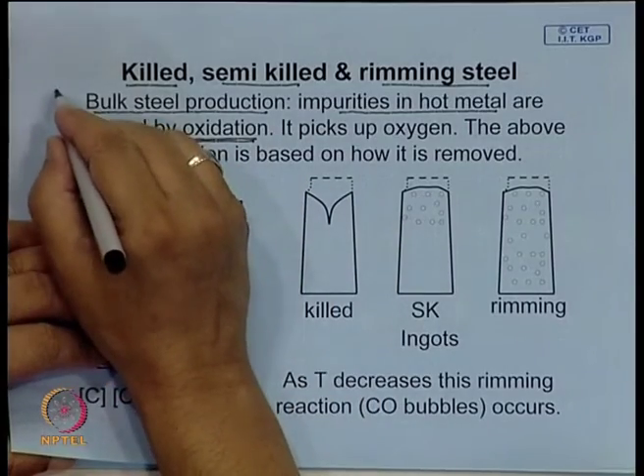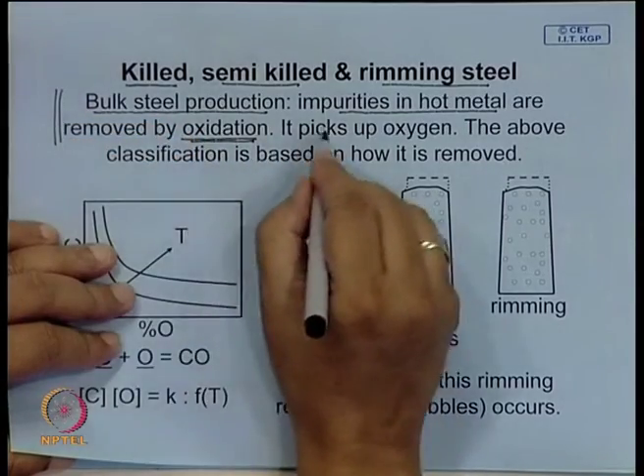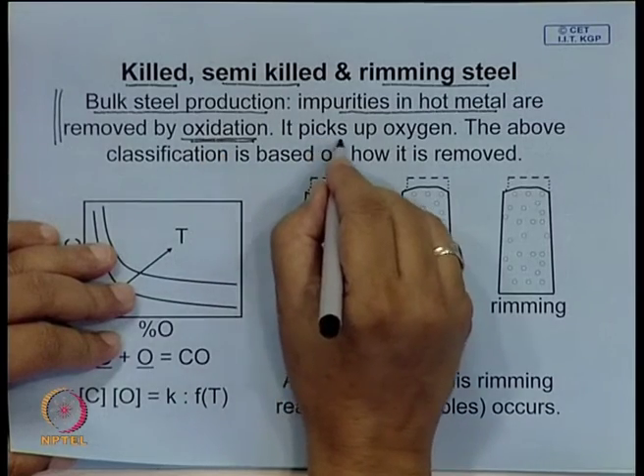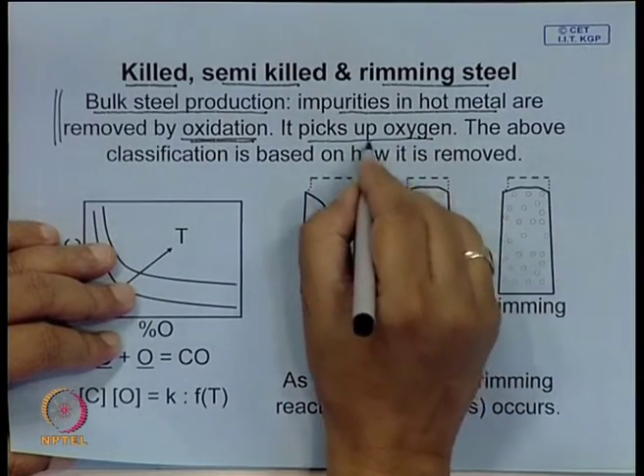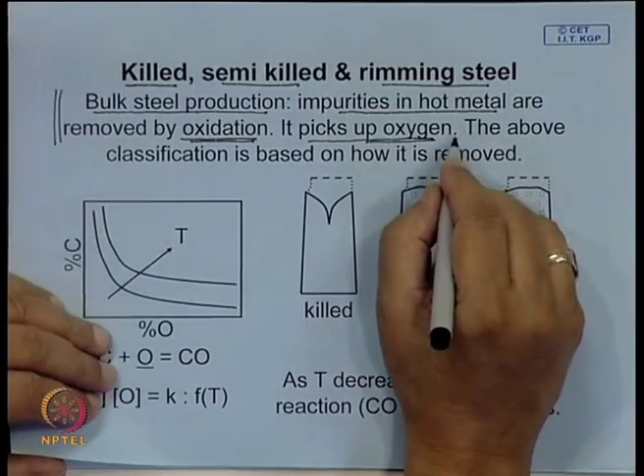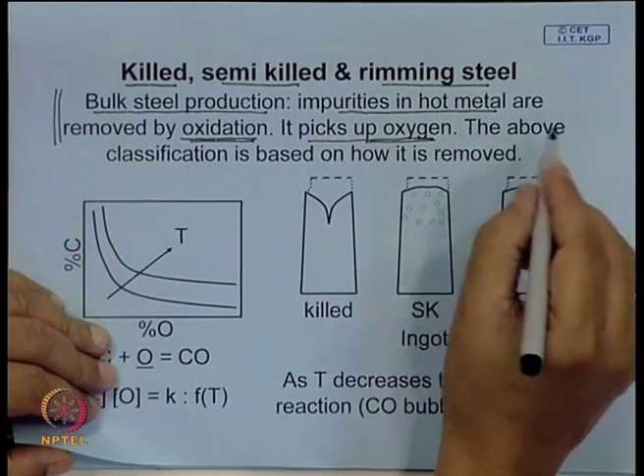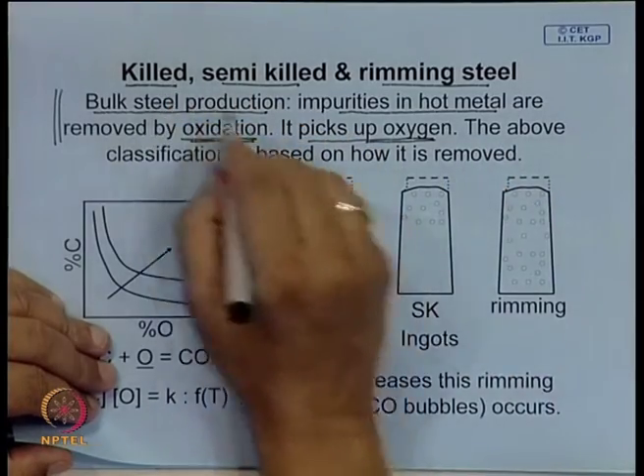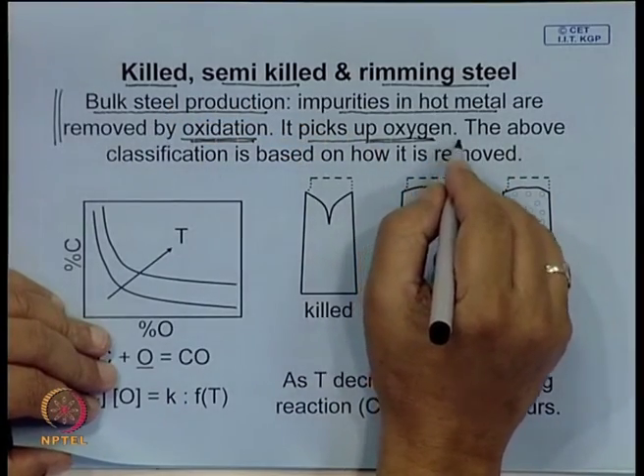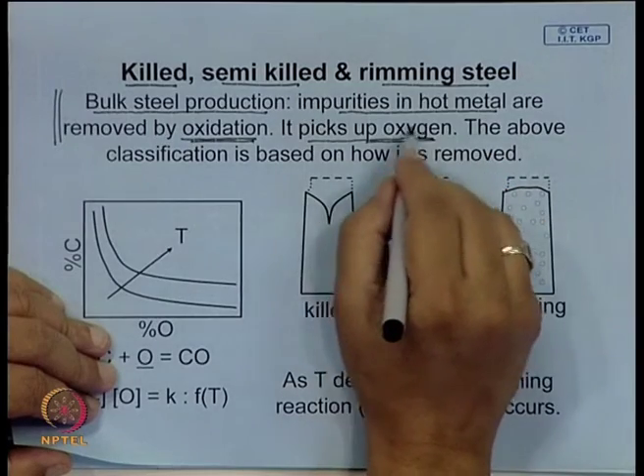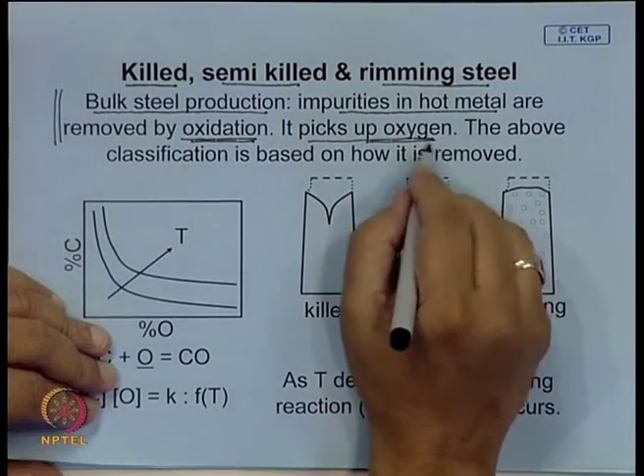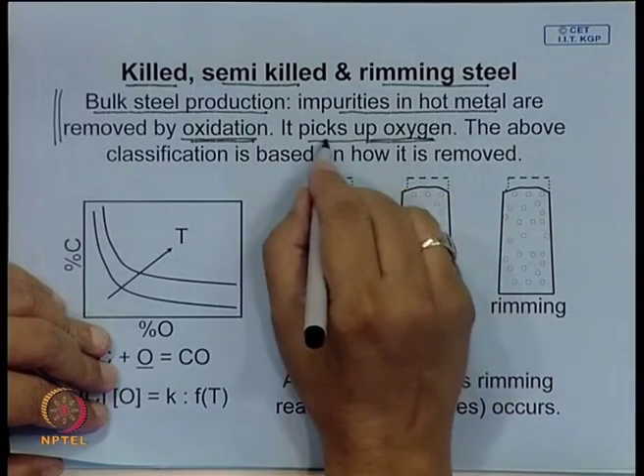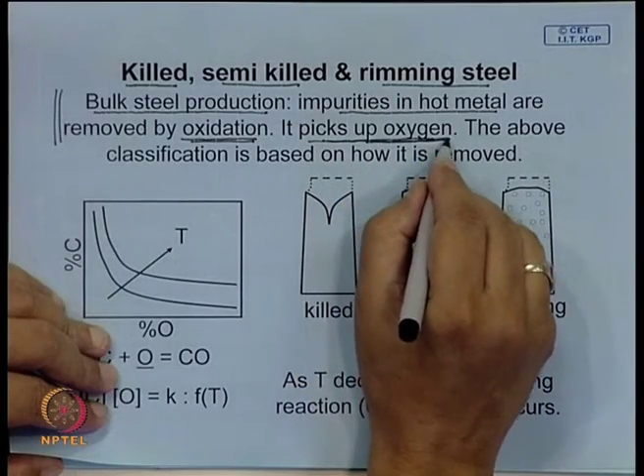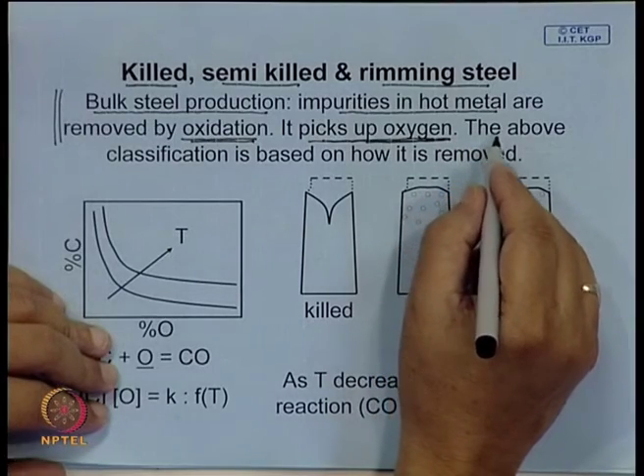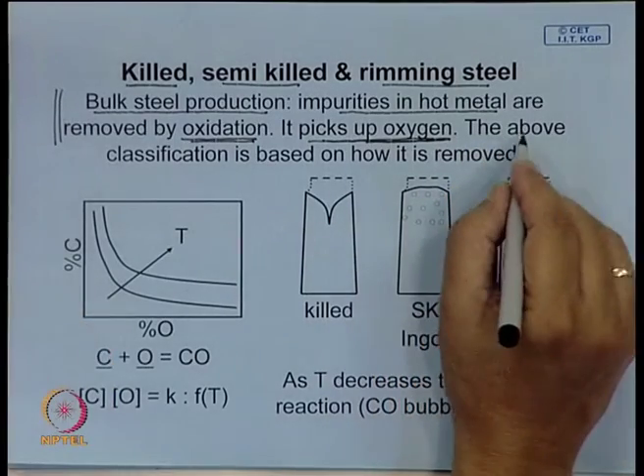And in the process, since the atmosphere that is maintained in the furnace is an oxidizing atmosphere, steel also picks up oxygen. This oxygen is in a dissolved state in liquid iron, and this has to be removed, because as you cool down, unless you remove it, if you do not do any special treatment, you often find that when this steel solidifies, there is a vigorous reaction taking place.